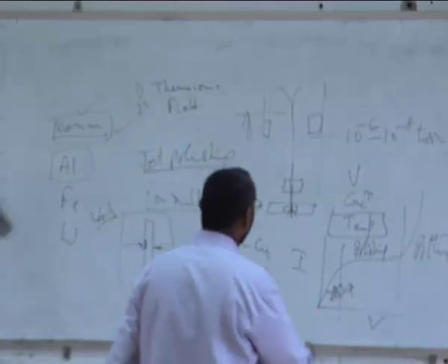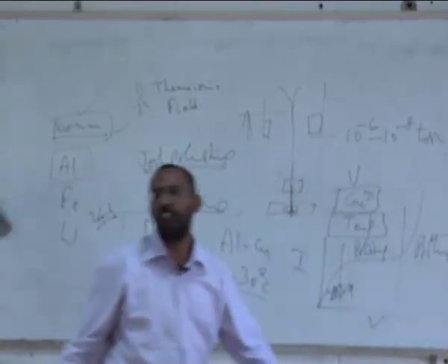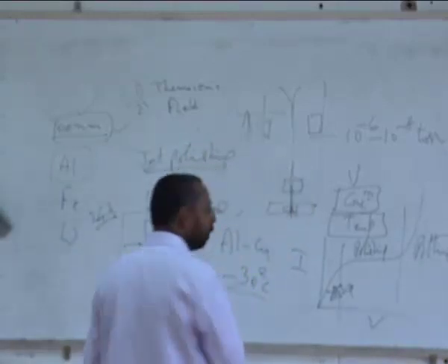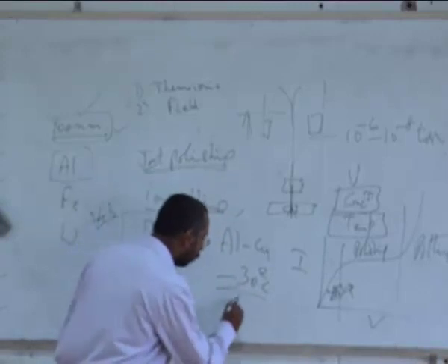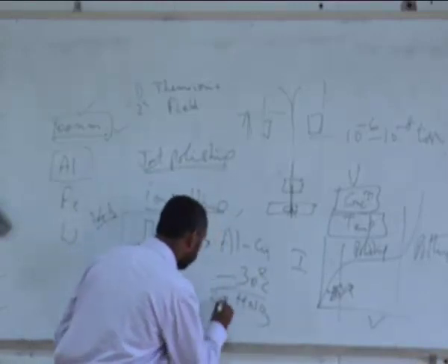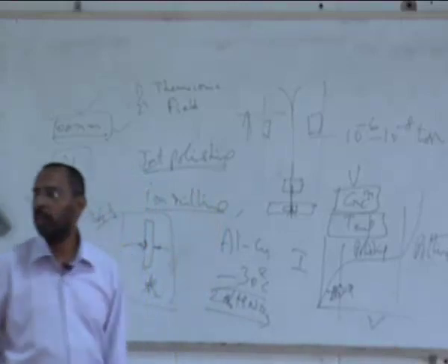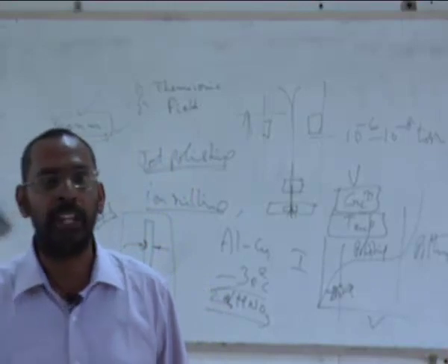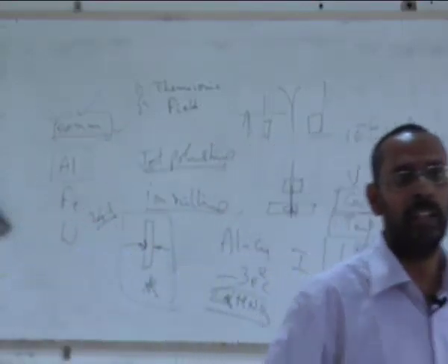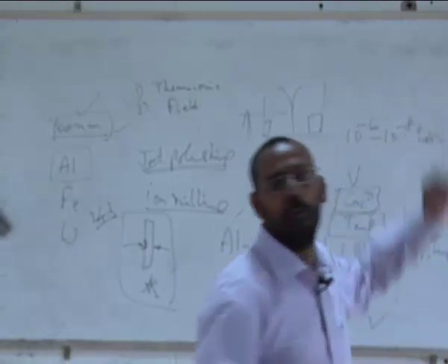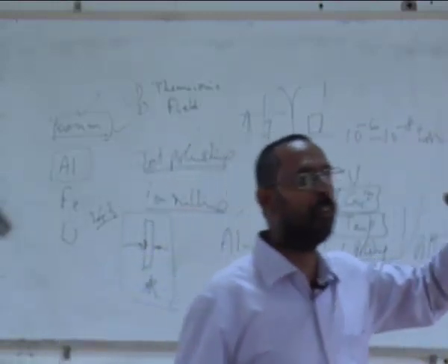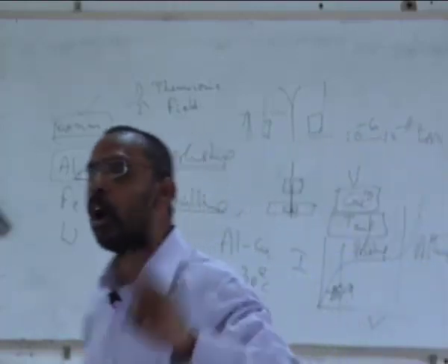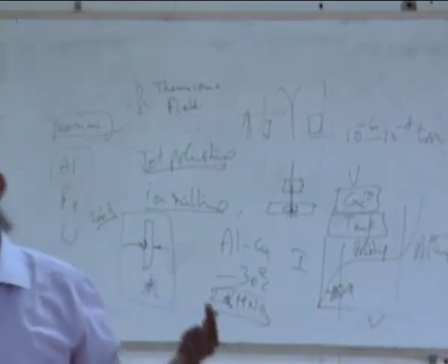And also what is important is what concentration you are using for different solutions. For example, for aluminum alloys, the best solution that is used is 20% HNO3 in methanol. Instead of 20, if I use 30 or 40, obviously the acid concentration I am increasing. So the dissolution is faster, and that will influence the whole process. So you need to identify the best solution concentration, the best temperature, the best voltage conditions. All these three are crucial if you are doing jet polishing.